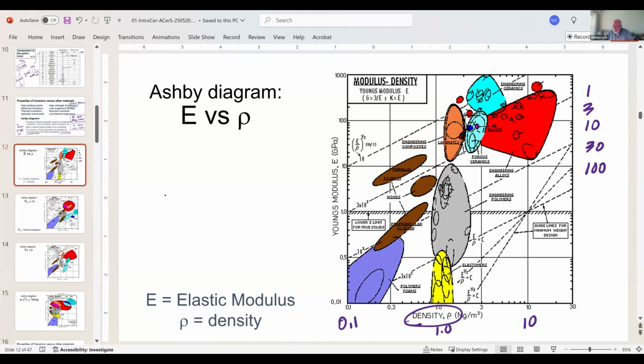So we have a number of things to point out, okay? This range up here, which I'll crosshatch for us, these are engineering alloys. And if you get into the books, he'll tell you what this one here is, and what these materials up here are, etc. First thing that you should see, looking at this from a general perspective, is that these are typically pretty high densities, from 3 up to about 20 grams per cubic centimeter. Engineering ceramics are here. Engineered ceramics have a high elastic modulus, but typically a narrow range of density, and lower density in the system than metals.